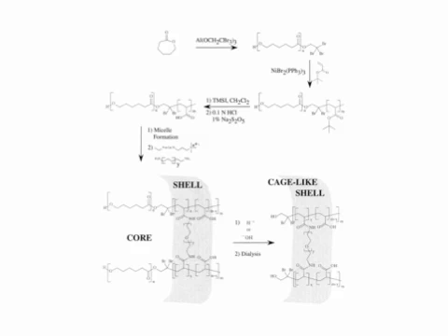Then they have one group that they modify into a tertiary bromide group, and as a result you can turn it into a block copolymer, which they've done with a tertiary butyl group as protection. Then you get rid of the tertiary butyl group, so now you have your hydrophobic part and polyacrylic acid as the hydrophilic part.